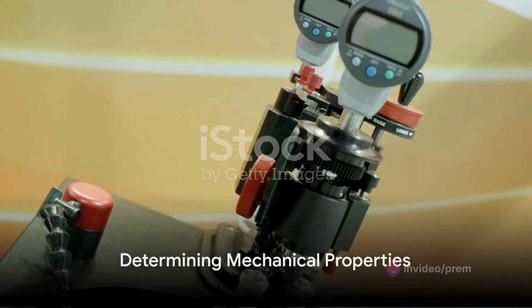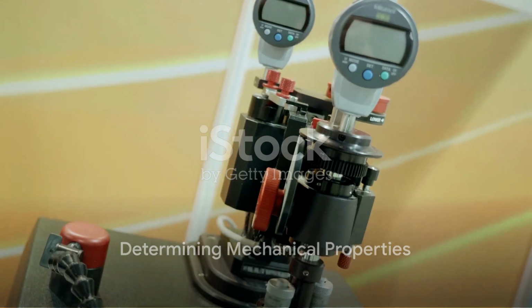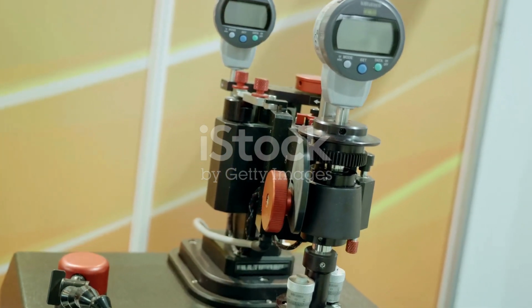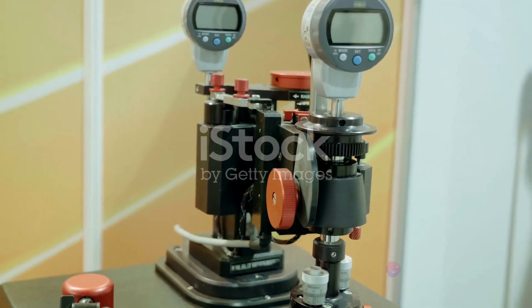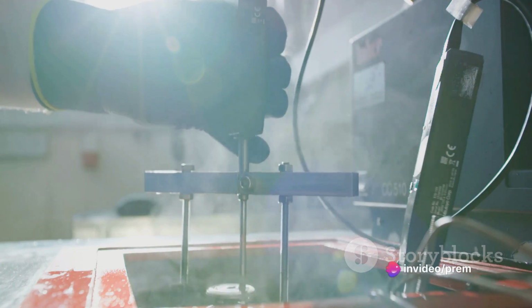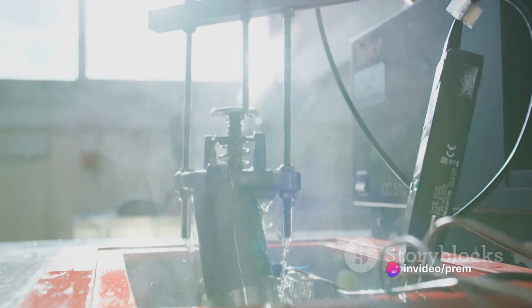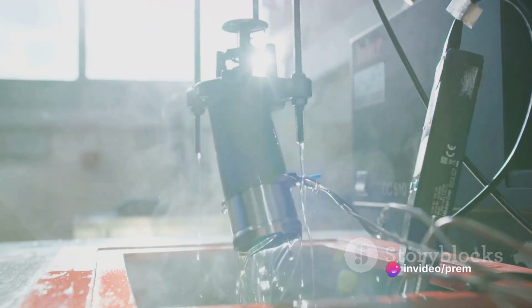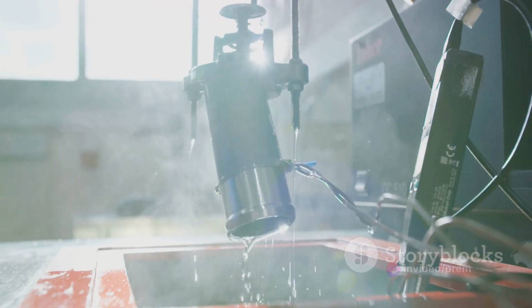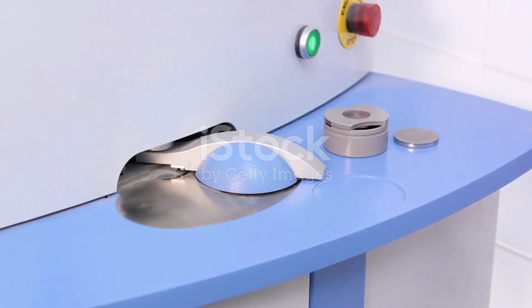Moving on to mechanical properties, the micro-hardness of the composites is determined using a Matsuzawa MMTX 7B Vickers hardness testing machine. With a loading of 100 grams and a dwell time of 10 seconds, 10 different readings are taken. The average of these values is then taken as the hardness of each composite.